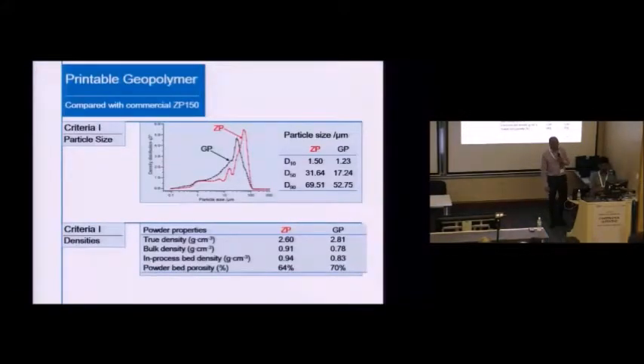So the way that we used is using a ZCorp printer, which is not a very large printer. And it's built to use gypsum. And the particle size distribution and particle flow are the important parameters. So what we did is we took the gypsum powder, which is the ZCorp proprietary powder. And we mimicked the powder distribution using geopolymer. Geopolymer is fly ash and sand. So we mix and we match the same particle size distribution. We mimic the same density, bulk density. So the powder bed is the same.